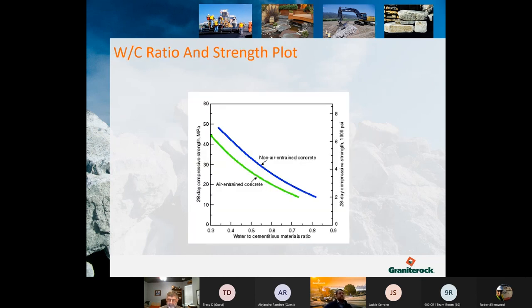To put that in a visual, on the bottom is water cement ratio, and on the right-hand side is compressive strength at 28 days in thousands. Common mixes are 0.50, which is right about 4,500 PSI, which is very common. And that's usually around a six sack. So as you go up in cement content, you also go down in water cement ratio.